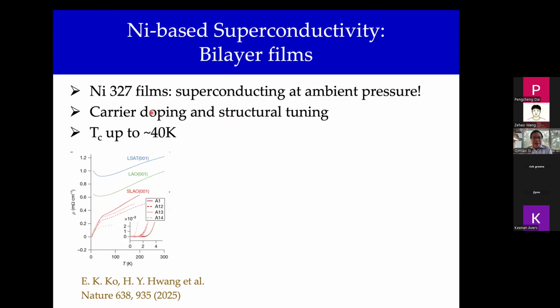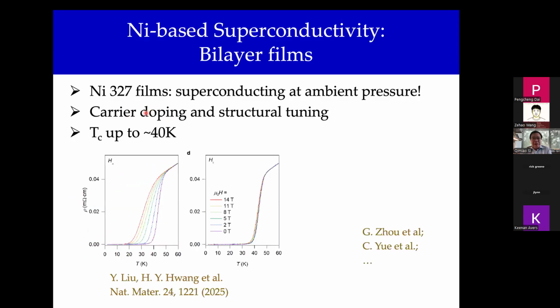And there's also various things that one can do, annealing, etc., that allows for carrier doping. So the upshot is that superconductivity still is happening at very high temperatures at around 40 Kelvin also, and this is another showing of zero resistivity in these films, and there have been a number of groups who have realized this kind of films with superconductivity at ambient pressure. So that's very exciting, and I will come back to some of the properties, including the properties about the superconducting state that have become accessible due to the realization of these ambient pressure, ambient condition superconductivity.